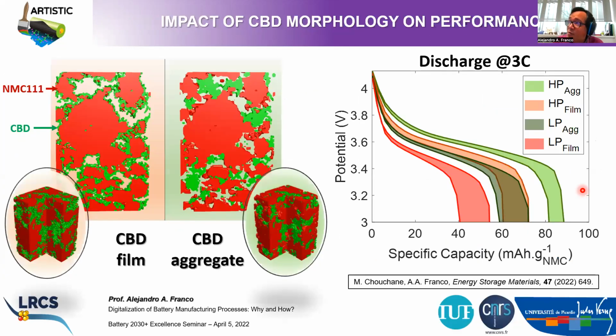And this is one of the latest works that we have published. So this was, I think, 1 month ago. And here we explore the influence of the CBD morphology on the discharge performance of NMC electrodes for high porosity electrodes, HP, and for low porosity electrodes. And what we show is that the electrodes having this aggregate CBD morphology perform better, okay, if you compare for high porosity the green curve with the red one, versus film, they perform better versus the film CBD morphology, and the same happens for the low porosity electrodes, right?